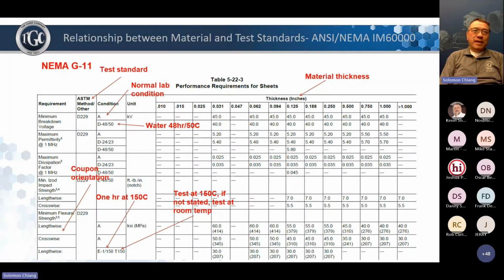And for high temp material, G11, which is a high temp glass epoxy grade, it will tell you the expectation at what they call elevated temperature property. That's to test at 150 degrees. And it also shows you the properties for different material thicknesses. As you can see, some properties are thickness dependent, some properties are not, but NEMA shows it all in one table.